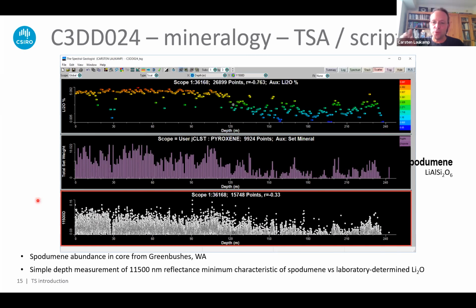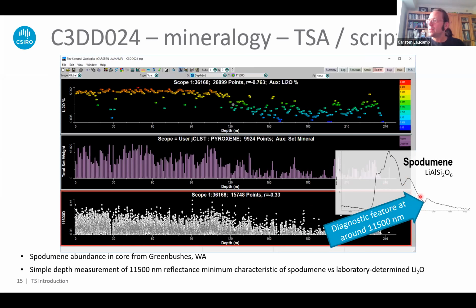And I showed before these spectral signatures in the thermal infrared of spodumene, because we are using this feature at 11,500 nanometers, the relative intensity of this one, to track the spodumene content. So there are various ways you can identify spodumene content. You can use either the matching algorithm, like in TSA, or you can use certain scripts that get you the relative intensity of certain features and can estimate the spodumene content from that.